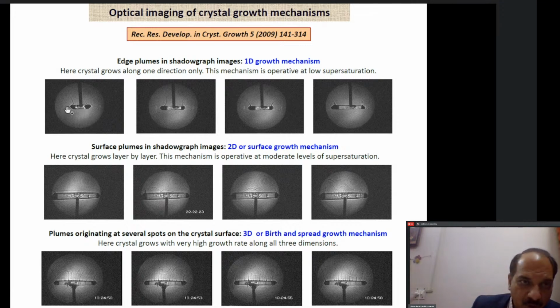You can see these plumes, small black lines which are emanating from the edges of the crystal, and these black lines are because the crystal is growing mainly along this direction and this direction. So this we called edge plumes in shadowgraphy images, and this is representative of the one-dimensional growth mechanism. Here the crystal grows along only one direction, and this mechanism is operative at low supersaturations.